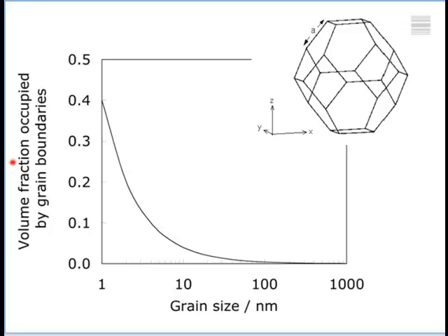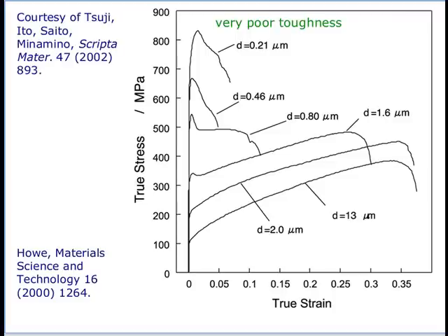If you eliminate the work hardening mechanism, then you will have plastic instability, and as soon as you pull your tensile specimen and it yields, it will fracture. So here is an illustration of what happens. Here is for a large grain size of 13 micrometers. As I go down to 0.21 of a micrometer, my steel basically gives up and fractures. Okay, so you completely lose ductility because there is no mechanism for work hardening.